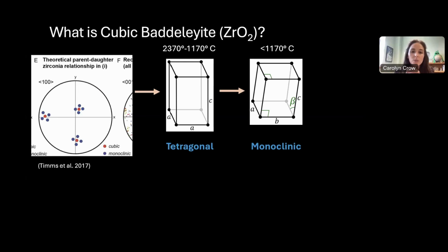And what that means is when we look at EBSD data, which is basically looking at a projection of where the C-axis is, if the C-axis was a flashlight, where would it be flashing on this circle on the left? Because we have those different shifts in multiple directions, instead of a normal pole projection plot where you have one really nice location for where your axis will be, you end up with basically a cloverleaf pattern, which is a relic of these shifts in terms of the structure. Okay.